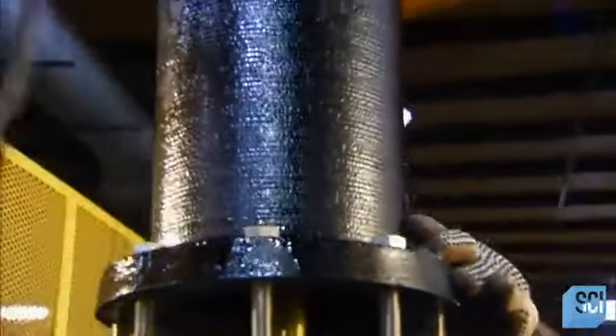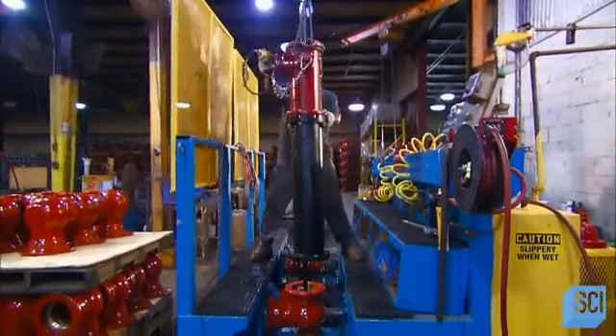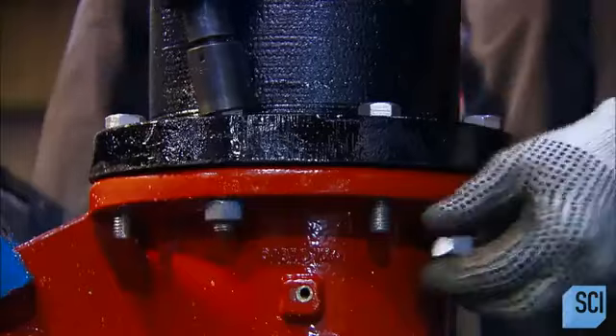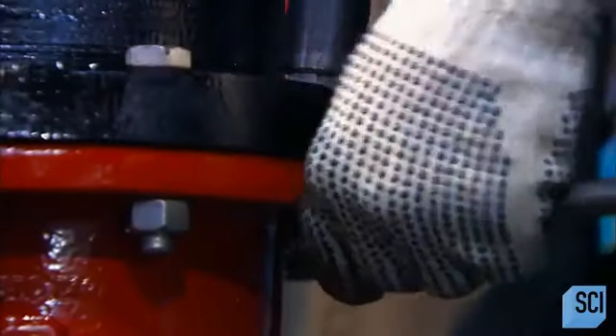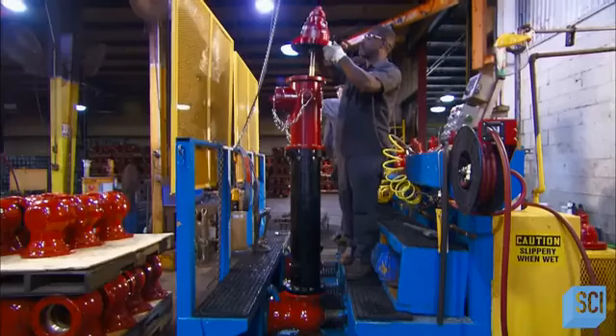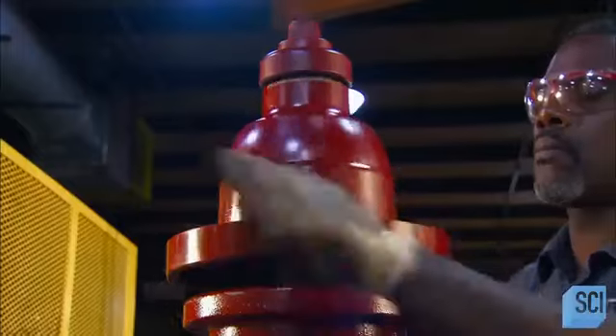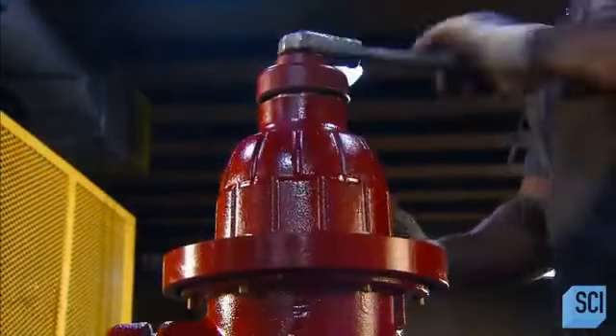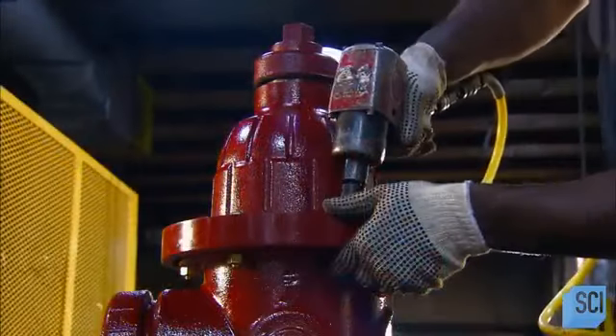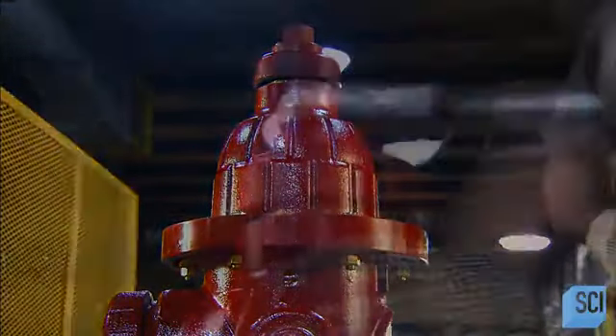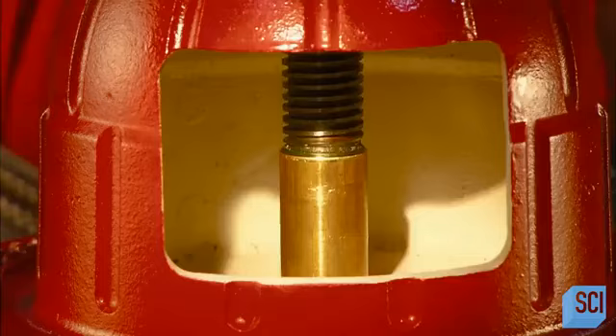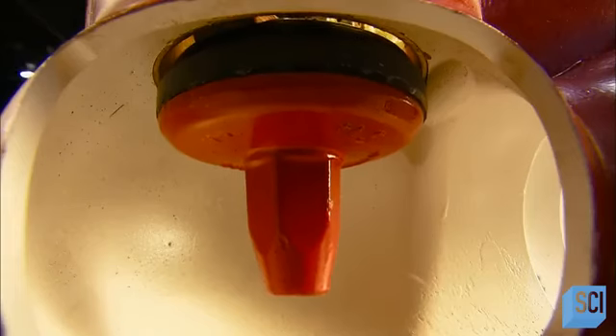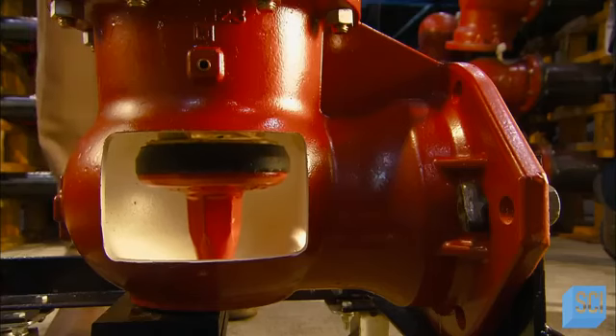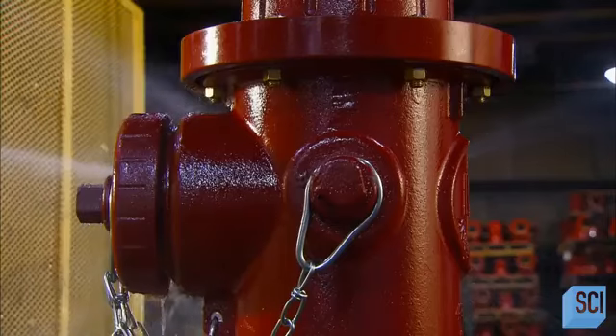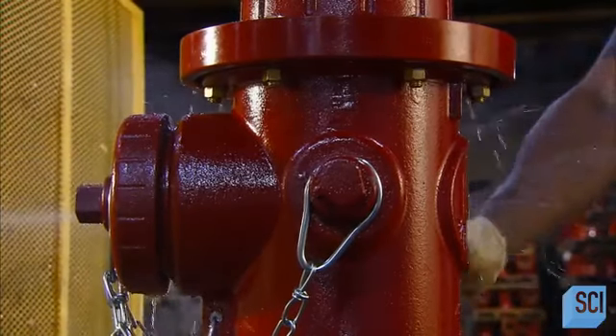Using a hoist, they lower the pre-assembled nozzle section over the stem and fasten it to the water main connector with stainless steel bolts. They lower the bonnet into place, bolt it to the nozzle section, then open the hydrant for a high-pressure test. They turn the operating nut to allow water to flow through. But first, they have to force out the air inside the hydrant with water.